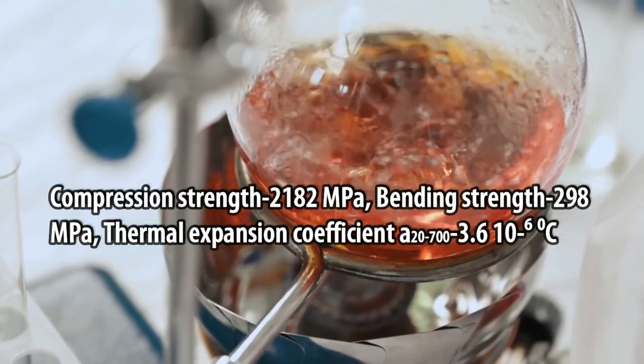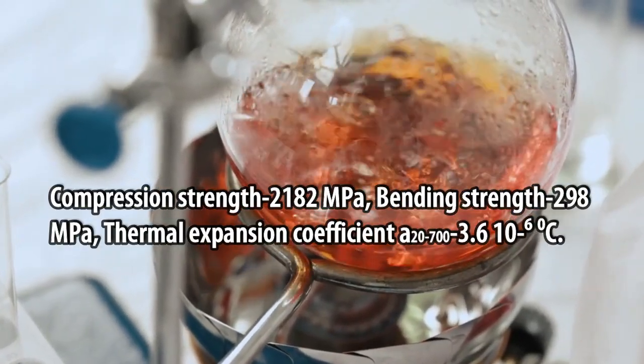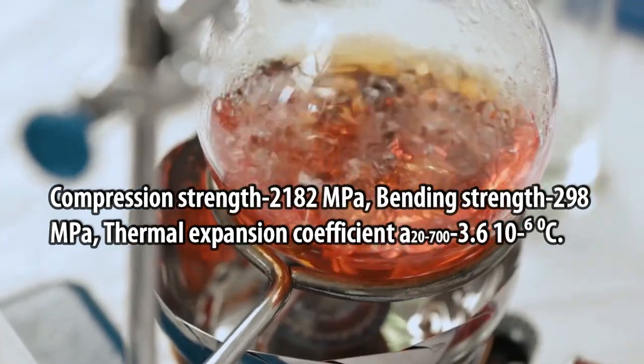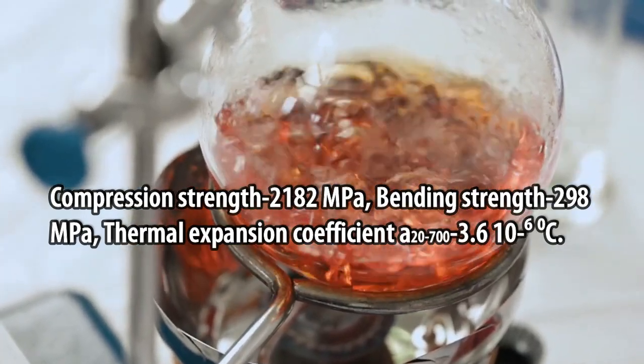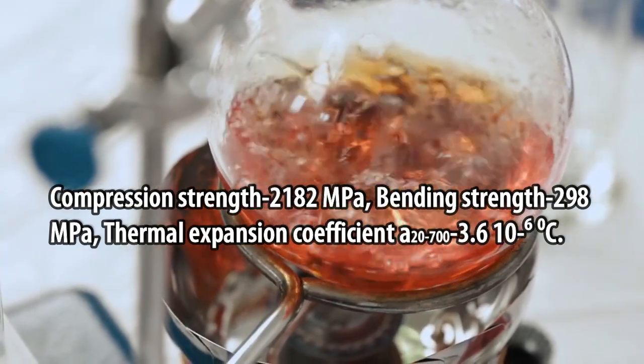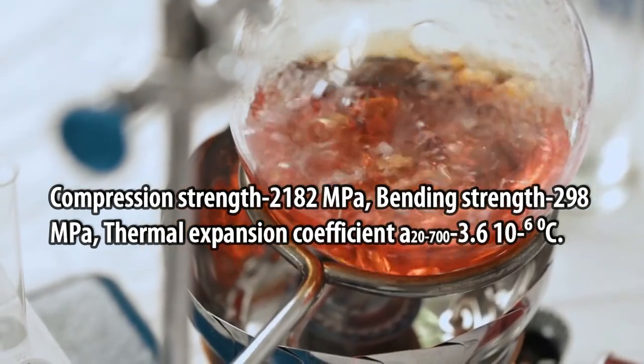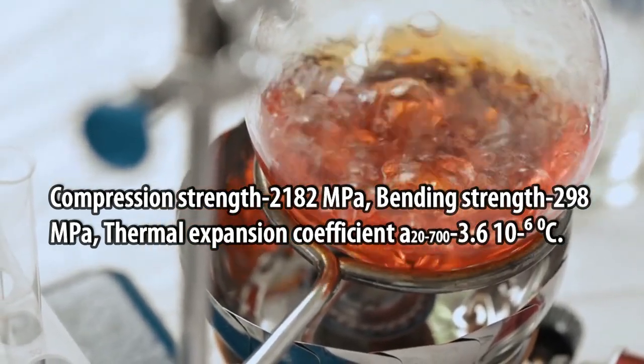Compression strength 2182 MPa, bending strength up to 298 megapascal, thermal expansion coefficient a 20-700 is 3.6 times 10 to the power minus 6 per degree Celsius.